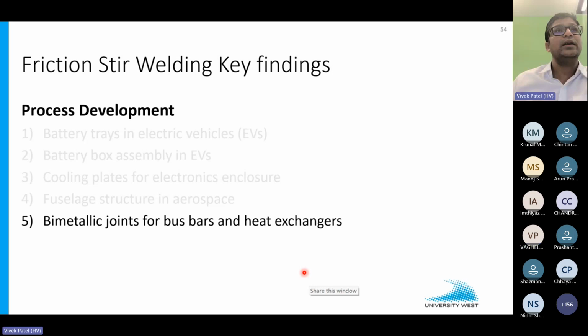Then the last applications for bimetallic. This is a new activity we are doing now, and we are trying to weld aluminum on the top and copper on the bottom. That's a typical application. In one of the cross sections we can see here, on the top you have the aluminum, the bottom is copper, and we designed our own tool so that it can work effectively on the copper side and the aluminum side, because it's always tricky to mix copper with aluminum because of the difference in melting point and, of course, the properties.